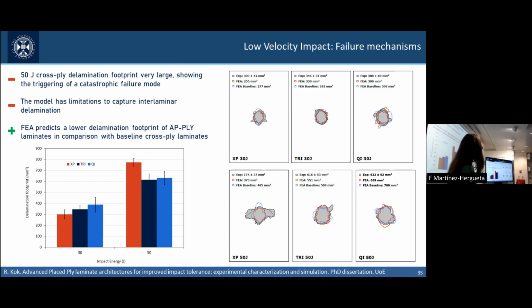Another point is that since we've got numerical models, we use them also to evaluate virtually the response of conventional angle-ply laminates. We didn't manufacture them, that's part of our future work, but at least we did some numbers, and what we found out is that the predicted delamination footprint of the baseline laminate is larger. So that gives us some hope that the AP-PLY laminate will perform better on impact.